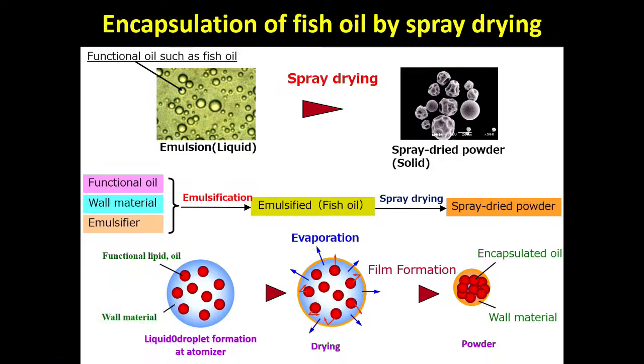So this emulsion contains the functional oil, such as fish oil, the wall material, and the emulsifier. With these 3 ingredients we get the powder. The first process is emulsification, and the second process is spray drying. When we want to make spray dried powder, every time we have to think about the first process, the emulsification process, and then the liquid droplet formation by the atomizer.